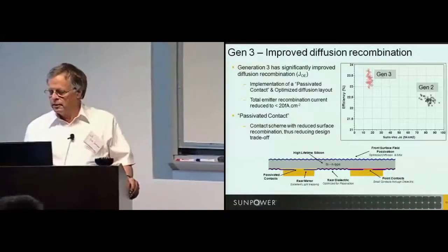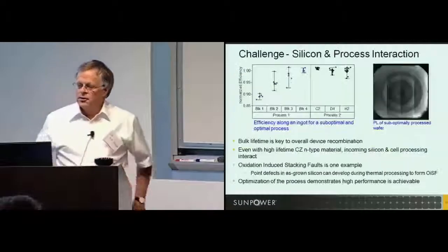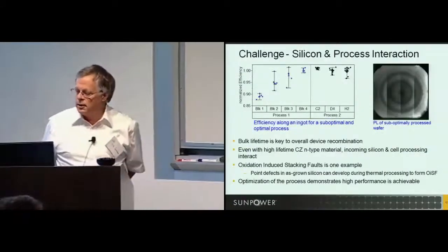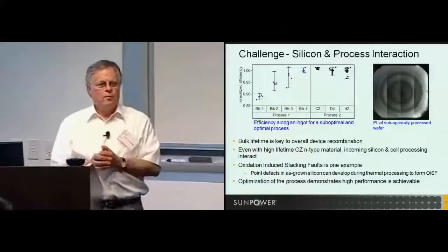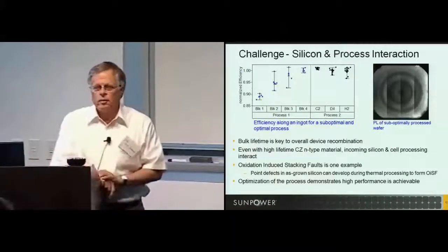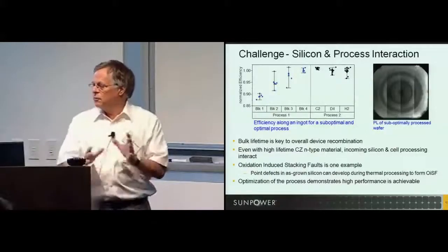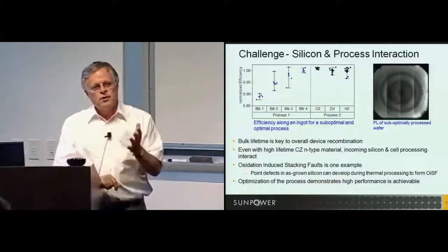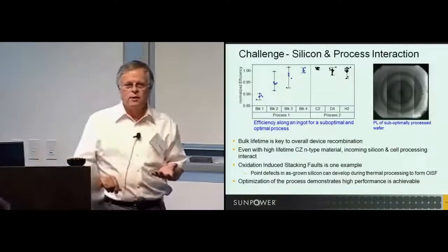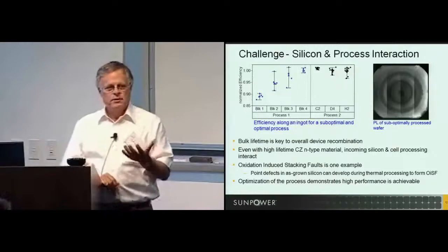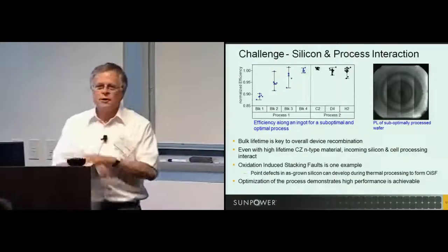They make some pretty good LEDs, actually. Let's see, here's a good example of that. We use a lot of emission. We run our solar cells backwards, both in production and in the laboratory, all the time in an LED mode. This shows a full-size wafer running as an LED, and you're seeing the light emission from it. Now, unfortunately, you can't see it because it's in the infrared, but it's so strong that you can easily take a picture of it with a standard CCD camera or a standard cell phone camera.